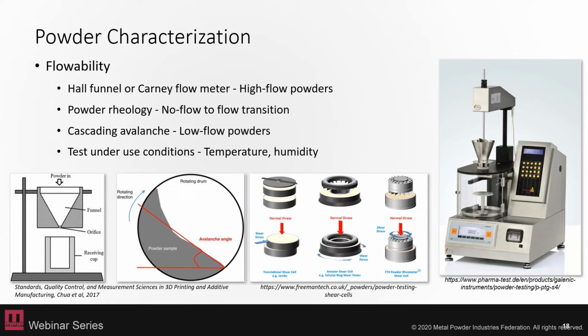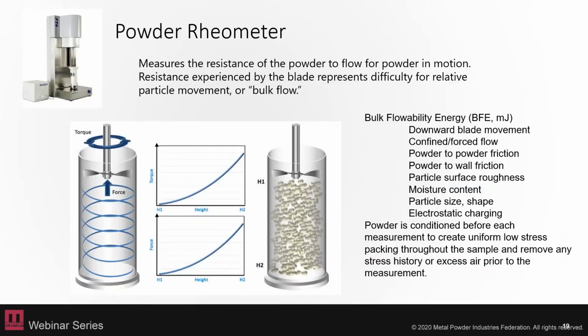For example, with this powder rheometer, there's a kind of propeller that goes through a set volume of powder, and it measures the resistance of the powder to flow for that specific powder bed that would be in motion. And that resistance is correlated back to particle motion. And this particular setup can give you a lot of different information from your powder bed, including your bulk flowability